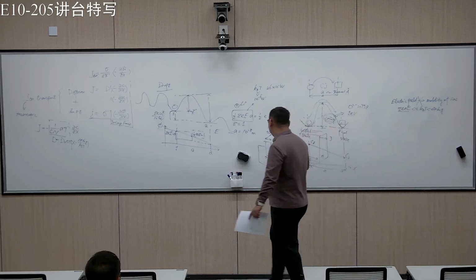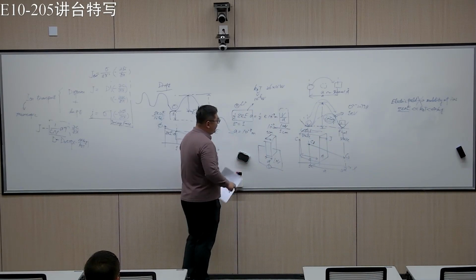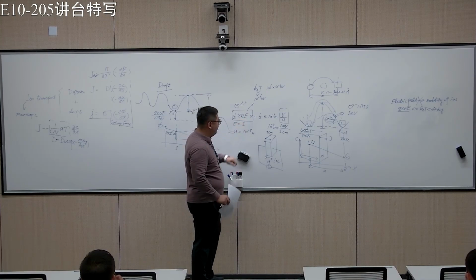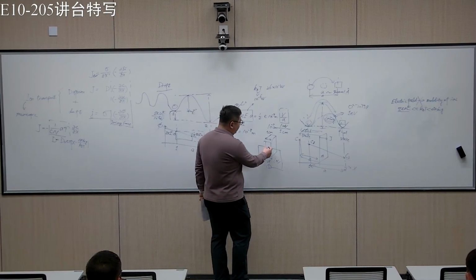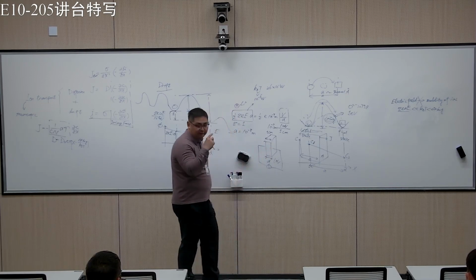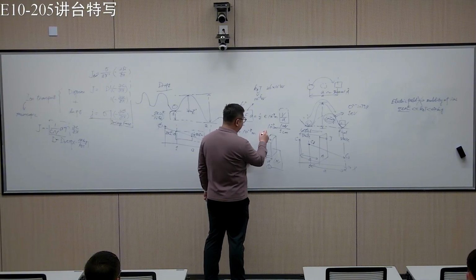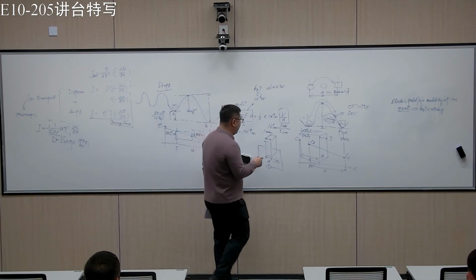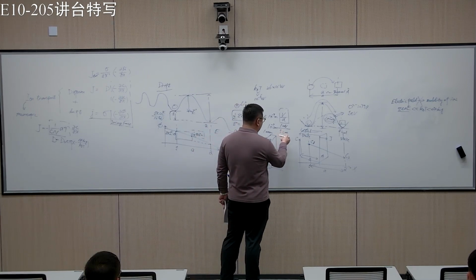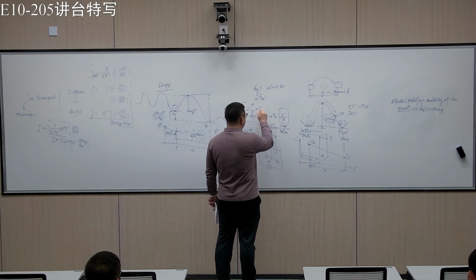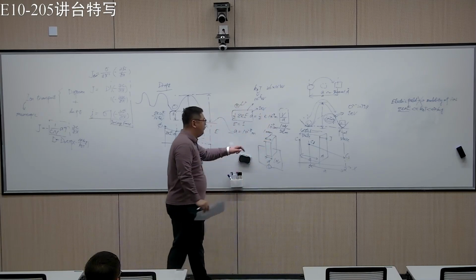There's only one special case, where you increase this to really big. Imagine that if I don't have the pellet but a thin film, let's say only 10 nanometer, then now here is 10 to the minus 6 centimeter. Then this can be something like 1 eV. It can be really large.